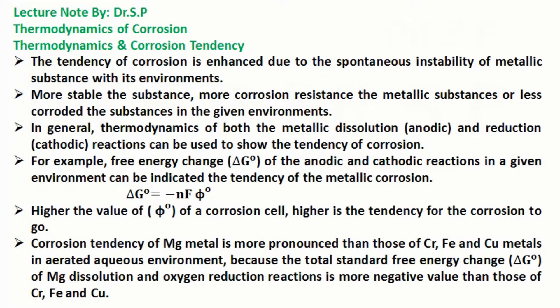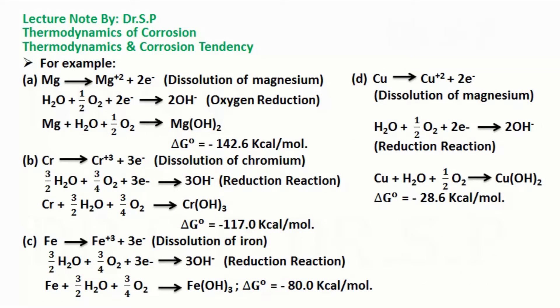In aerated aqueous environment, the total standard free energy change (ΔG°) of magnesium dissolution and oxygen reduction reactions is more negative than those of chromium, iron, and copper. The large negative value of the change in free energy indicates a pronounced tendency of magnesium to react with aerated aqueous environment. From these thermodynamic data, it can be concluded that